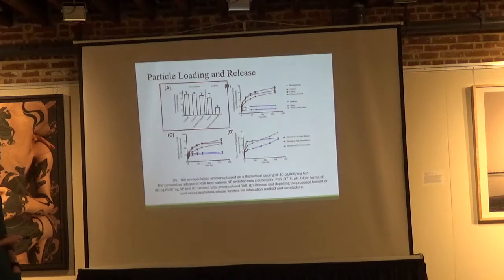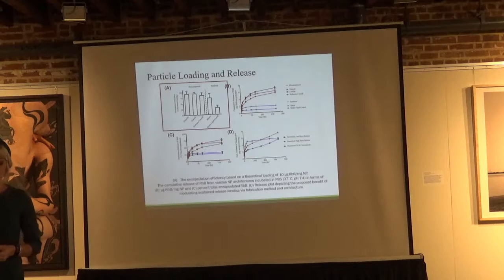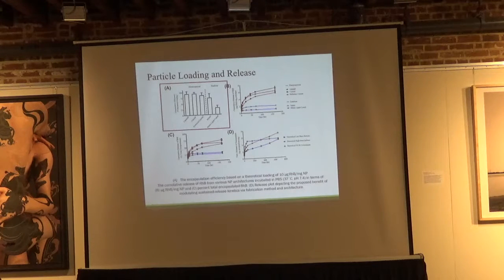And then here I just wanted to show, beyond the nice release characteristics, which we've more thoroughly characterized here, we can see from panel A that electrosprayed formulations after loading load a higher amount of active agent. It's really the synthesis process. You don't have room for these small hydrophilic agents to leak out during the processing. And then we have the emulsion base where you get lower loading. It gets even worse when you put a lipid coating on it.